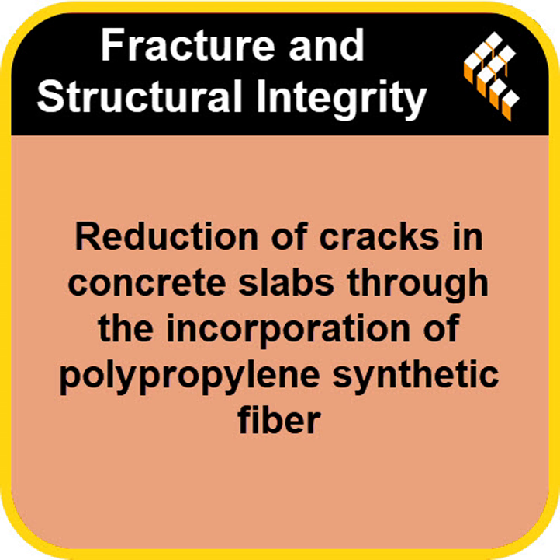It is. This is the core conflict of the research, what they call the dosage dilemma. Exactly. You'd think if a little fiber is good, a lot must be fantastic, right? Seems logical. But the research shows the opposite. The optimal amount is absolutely critical. Once you go over a certain limit, maybe around 1.5 kilograms per cubic meter, the fiber stops helping. It actually starts to interfere with the mix. You get more porosity, not more cohesion. You're basically introducing millions of little things that get in the way of the cement paste bonding. So you can actually cause cracks with the very thing you're using to prevent them. You can. It's a very fine line. We saw other studies where too much fiber cut compressive strength by almost 16%.